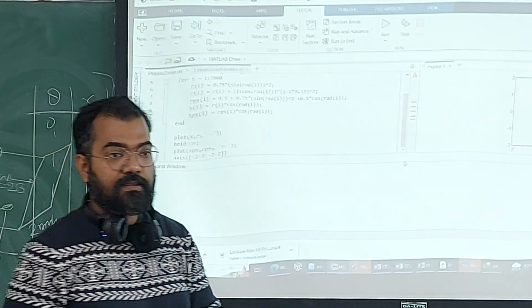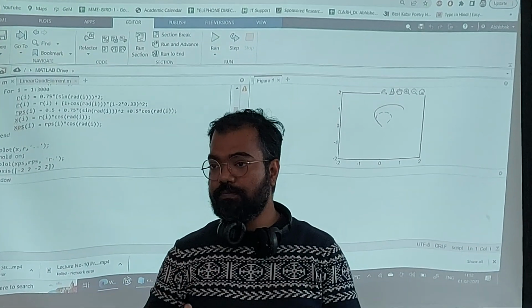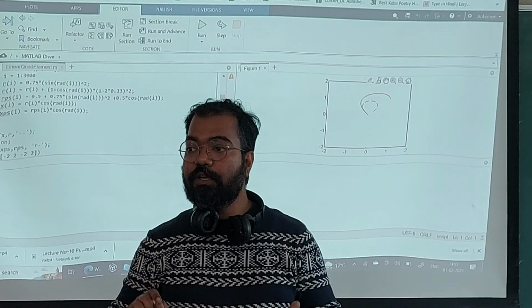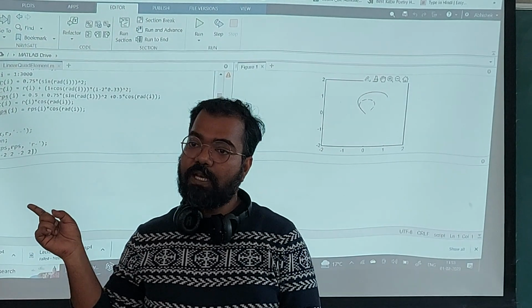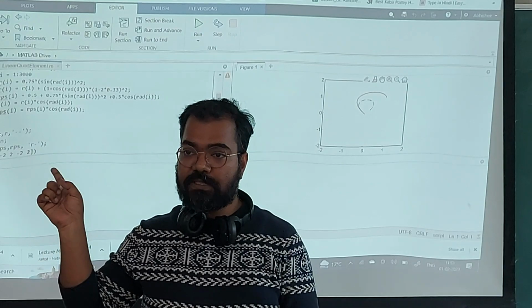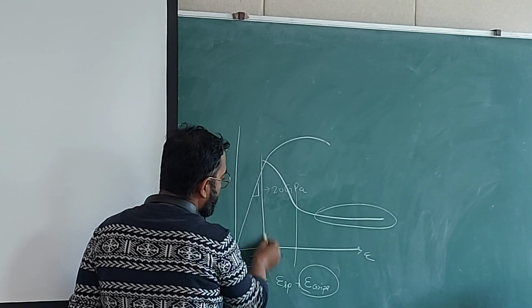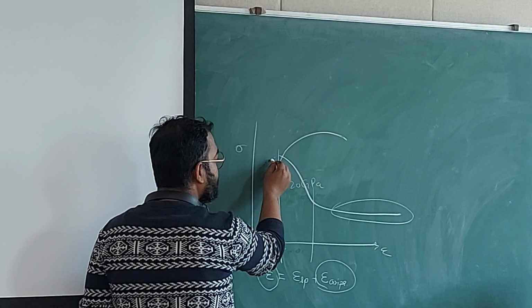Under plane stress, it becomes a game of individual component. So there you can't use whatever you have measured from the lab specimen. If that thickness and the pressure vessel thickness are different, you can't design it based on your lab value of K1c if it is not in plane strain condition. Understood?